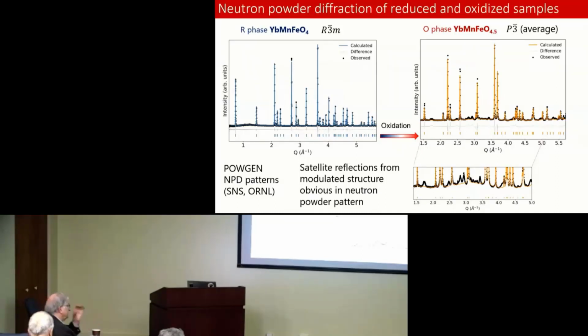So here's the rhombohedral phase, the reduced phase, which we also call the R phase. And it takes up exactly a half molar equivalent of oxygen and only up to that. And this is neutron data from POWGEN. And we're able to fit it okay. This is P-3 bar. But you can see it's not okay actually, because if you zoom in here, you have a ton of these satellite reflections in there.